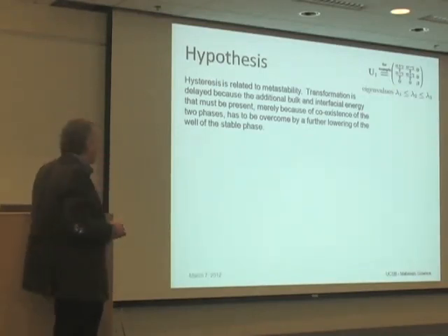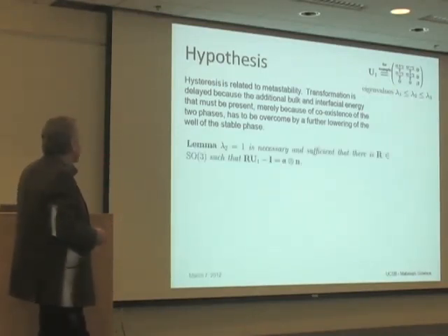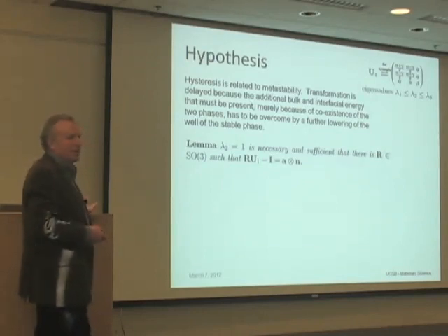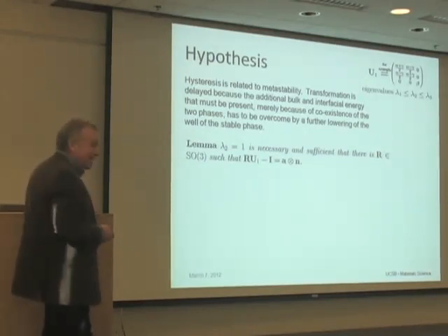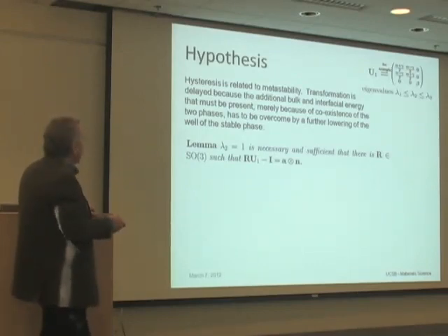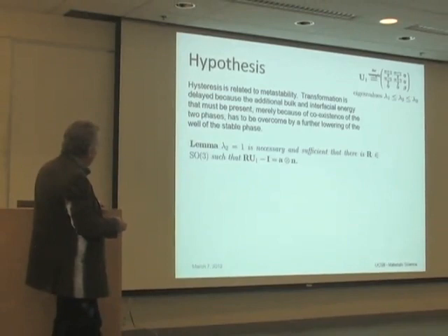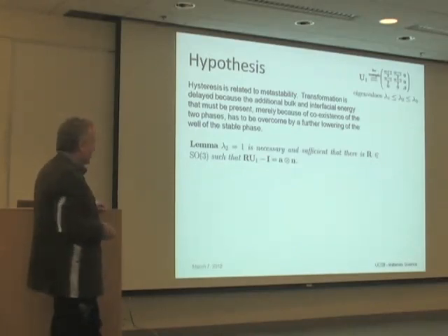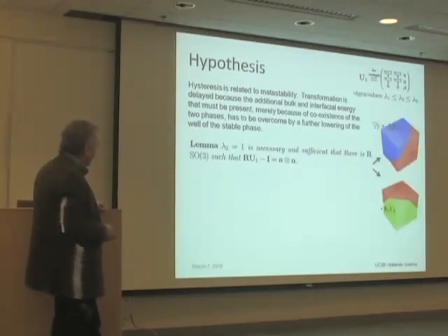Okay, so there is one mathematical result. As I said, the austenite is not compatible with a single variant of martensite, but it can be. The middle eigenvalue of that matrix being 1 is a necessary and sufficient condition that the martensite is compatible with the austenite. The compatibility condition between martensite and austenite is satisfied. If that's satisfied, I drew a picture. I took a matrix U1 whose middle eigenvalue is 1. And in fact, when it's satisfied, there are 2 solutions.